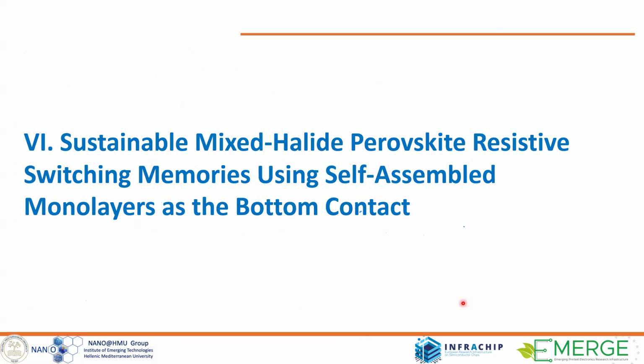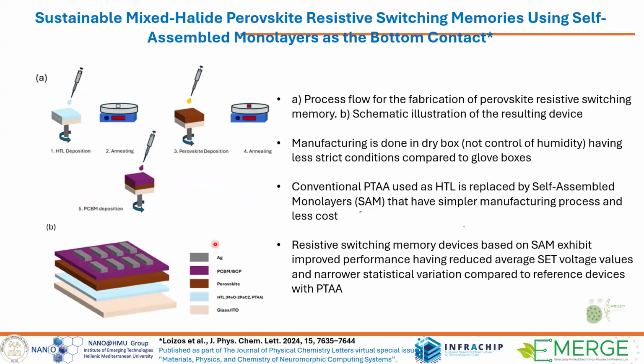So the last, before going to lead-free, in this work we wanted to replace one of the expensive materials of the structure. Usually we use PTAA, which is quite expensive, and we replace this layer with SAM, self-assembled monolayers that are very cheap. And we wanted to see how the performance will change by replacing PTAA, a very expensive polymer, with the simple SAM layer.